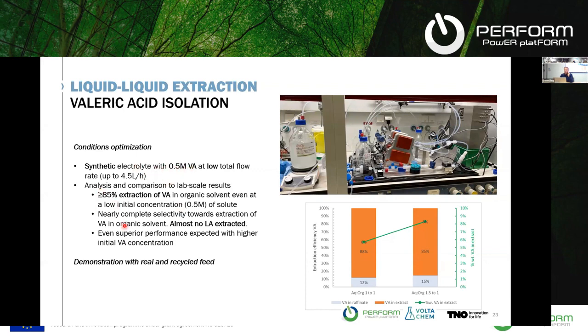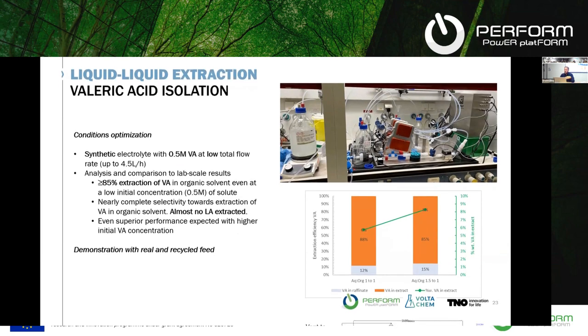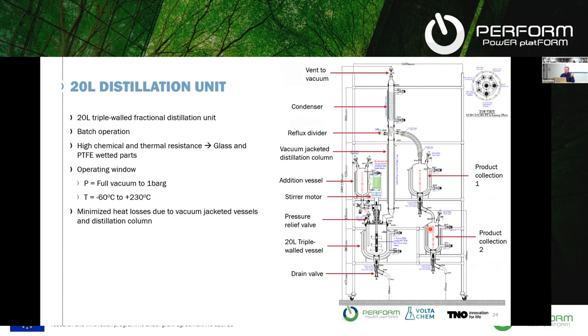With this type of solution, we were able to recover about 85% of the valeric acid that was in the mixture, using a water to organic solvent ratio of 1.5 to 1. These are quite nice results, and you end up with valeric acid in the order of 8% in your organic solvent. After that, you still need to separate the organic solvent that you added from the valeric acid, and this can be done by distillation.